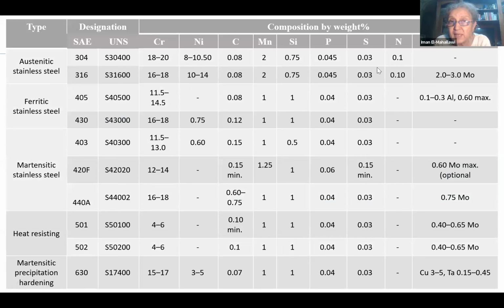In this context, in addition to what I have mentioned about the alloying elements, we have to notice that the two elements, sulfur and phosphorus, are undesirable. We rarely add them to steels except for special conditions when we need machinability, when we may add some sulfur, but usually they should be kept at a very low concentration. And this is the challenge with the alloyed steels, because in carbon steels, we may have a wider or more generous range for the sulfur and phosphorus than in alloyed steels, because their harmful effect is more pronounced on the properties of the alloyed steels if they are present in higher than the required values.